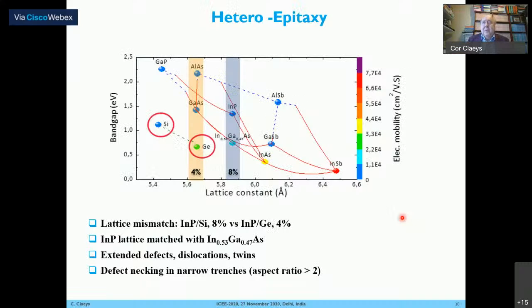But III-V materials are another problem. If you want to put, for instance, indium phosphide or indium gallium arsenide on silicon, you have a lattice mismatch of 8%. That's too much. That's going to give you a lot of defects. That's the reason why, for instance, you can first grow epitaxially a thin germanium layer, and on top of that, you can grow your III-V material. Because between germanium and indium gallium arsenide, the mismatch is only 4%.